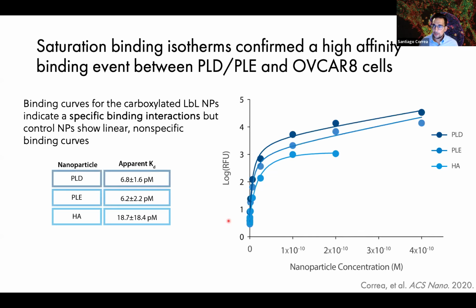When we look at this approach using our polypeptide coated nanoparticles, PLD and PLE, again, we see this hallmark curve indicating specific interactions. And when we are able to fit this data, we see single digit picomolar affinities for ovarian cancer.